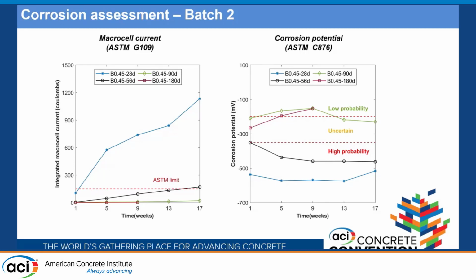So now let's move on to the batch 2 results, where I've changed the curing period. And you can see that the macrocell current, the blue line, indicates the value for 28 days. And as I increase the curing period, you can see these values fall within the limit, up to 5 cycles of exposure. That is the duration that I tested the specimens for batch 2. And also for corrosion potential, you can see that 28 and 56 days fall in the category of high probability, whereas with 90 and 180 days of curing, it now changes to a region of uncertainty and finally to low probability of corrosion, 90% probability of no corrosion.